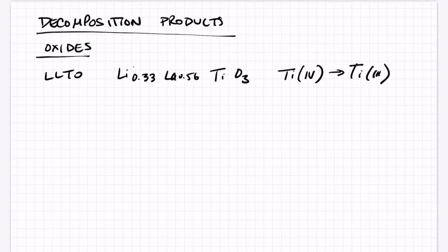And so typically you don't find titanium 3+ as a thermodynamic equilibrium product, like you wouldn't normally find Ti2O3, but you would find the more thermodynamically, energetically favorable product, which is TiO2. But at these interfaces, these species can be stabilized due to higher energies at the interfaces or voids and what have you. You can have all these metastable species, and so you can encounter titanium 3+.